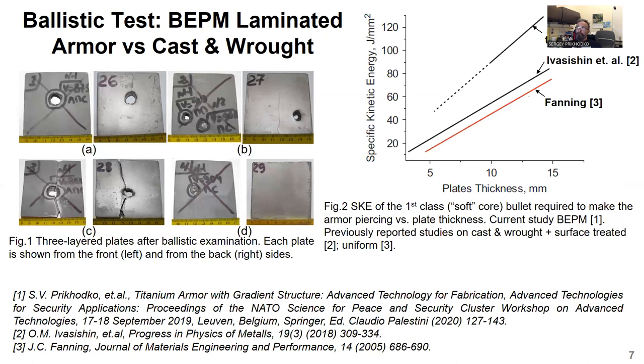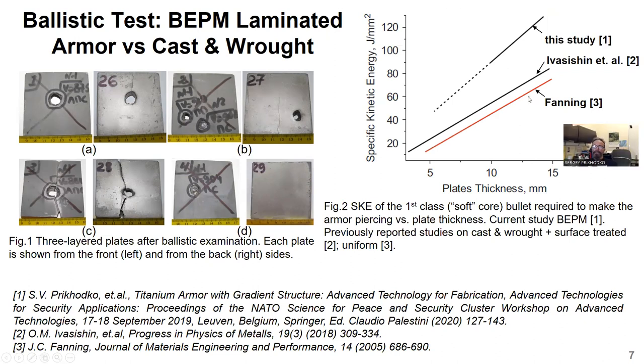Our ballistic tests prove the validity of expected behavior of laminates. Considering the kinetic energy of the bullet, its type, velocity, and thickness of armor plate, the specific kinetic energy required for armor piercing can be calculated. The three-layered laminates from this study, in the graph number one, show significant improvement compared to currently suggested by industry titanium armor fabricated using cast and wrought technique, shown here on the chart number three. It is worth mentioning that the powder metallurgy fabrication we used is about half as expensive compared to the cast and wrought technology currently used for titanium armor.